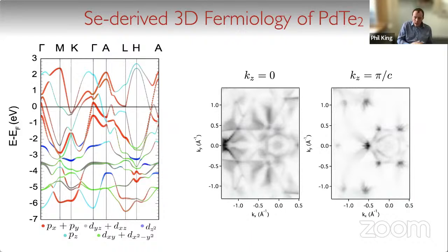And one thing that immediately leads to is a rather three-dimensional character of the Fermi surface in this material. Although these are layered van der Waals materials, the chalcogen states are sitting either side of the van der Waals gap, and so there's still finite, in fact quite significant, hopping between these states across the van der Waals gap. And that gives us a rather three-dimensional character to the electronic structure here at the Fermi level. And you can see that, for example, in these measurements here performed in the gamma plane of the material, and in the A plane of the material, where you see a rather dramatically different Fermi surface here, governed by these tellurium p states.